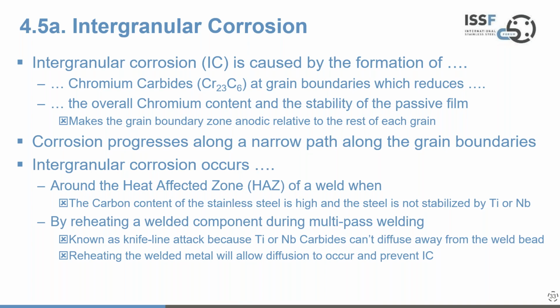But also, if you're undertaking multi-pass welding, by reheating a welded component multiple times, and even if you've got titanium or niobium in there to mop up the carbon, those carbides cannot diffuse away from the weld bead, and you get a phenomenon known as knife line attack. However, at the end of the welding process, if you reheat the welded area, this will allow diffusion to occur and prevent this type of intergranular corrosion. So these things can be overcome.